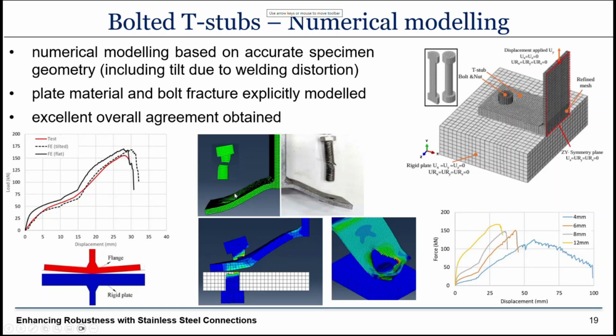After obtaining a good agreement, we carried out parametric studies, and we varied the thickness of the plate and also the location of the bolts. And when we went to very thin plates, we shifted the failure mode from bolt fracture to fracture of the plate material at high deformations due to membrane action in the vicinity of the bolt hole. These are some load displacement curves. The blue line that seems to have a more gradual loss of strength corresponds to that failure mode where we have a slower loss of material with progressive fracture. When we have bolt fracture, at the end of the response, the fracture is more abrupt.